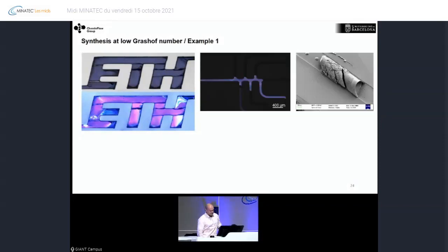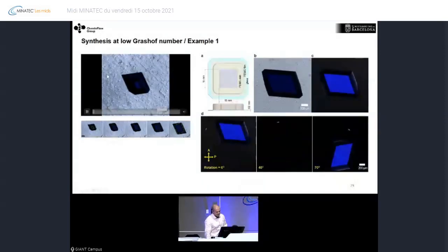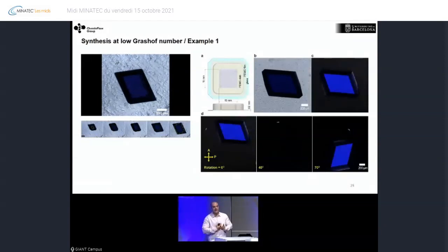But look at this here. By playing with the microfluidic device and the fluidics, we were able to generate single crystals that were millimeters in length. So this is a remarkable finding. And as you see, now we don't have this polyhedral shape anymore. What we have here is this semicircle shape of the MOF crystal. Then, if we change the microfluidic device, we can also change the shape of the crystal. And we can, for instance, generate films, as you see here. Okay, so this was a very interesting topic, and we are continuing working on that.